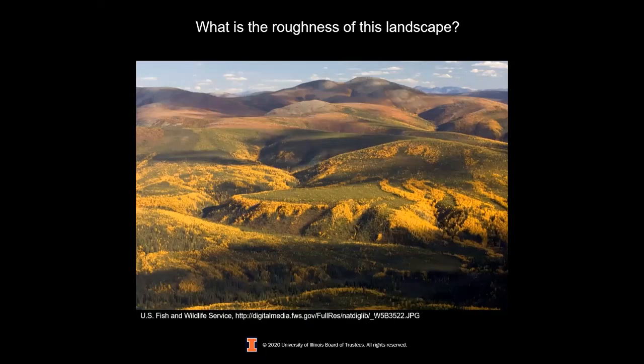The not really officially the right way, but what I see a lot of people doing if they want to do comparison is find a good field of view and a good number of nanometers per pixel and then be consistent across samples. But that's not an absolute number. I think the questioner was asking, how do you find sort of a more intrinsic value? And for that, you do want to slowly increase your field of view while keeping the same number of nanometers